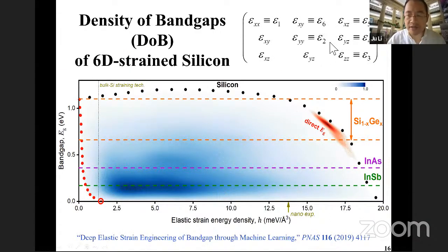And it's actually quite difficult to visualize that kind of high-dimensional function. So what you are seeing here is the distribution of band gap as a function of the elastic strain energy density, because this is a scalar, in milli-electron volts per cubic angstrom. So this is how much energy you're willing to put into the crystal. And for, let's say, 5 meV per cubic angstrom, there are actually infinite combinations of elastic strain which will give you this kind of elastic strain energy density. It could be compressive, it could be shear, it could be tension.